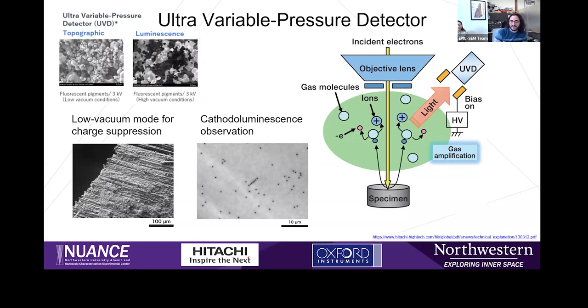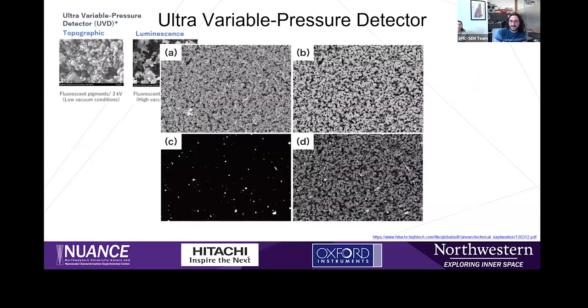In this image, you can see the areas of crystalline dislocation in this gallium nitride substrate. Now there's no spectrometer attached to this, so we'll only be able to do CL imaging, not CL spectroscopy with this detector. But here's another example of the different data you can collect using the UVD as a CL detector. So A is an SE image of a rutile anatase mixture, which are both TiO2 polymorphs, so you can't really see a difference there.